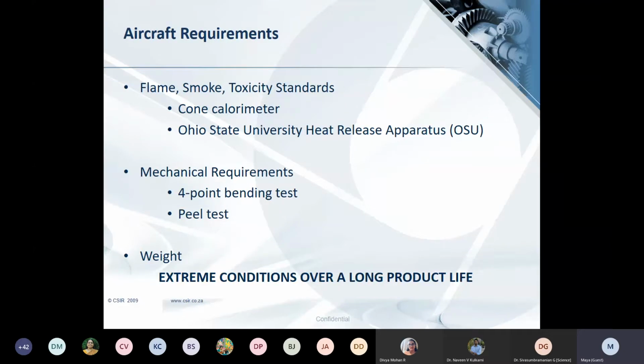Now, according to FAA regulation, which is the Federal Aviation Admin Regulations, it is mandatory that if you want to use materials in aircraft, it has to be tested on the OSU. So that's why we've tested on both the cone and the OSU. The mechanical requirements comprised of a 4-point bending test and a peel test. And we also had to make sure that the weight did not exceed that of the current panel.